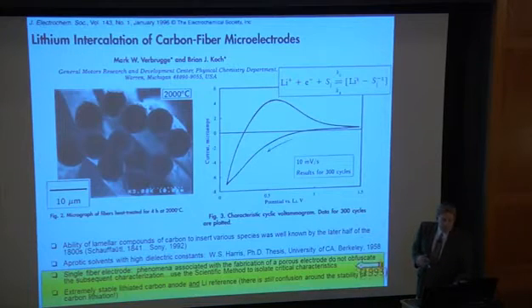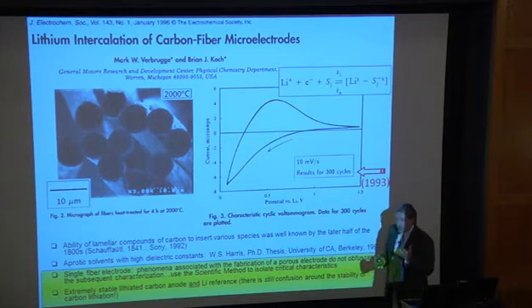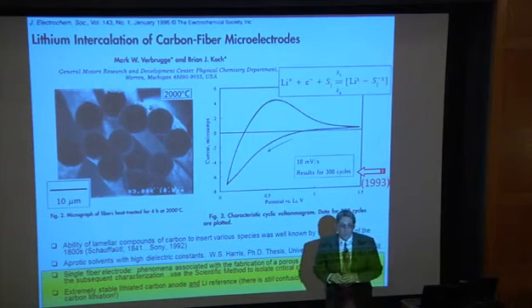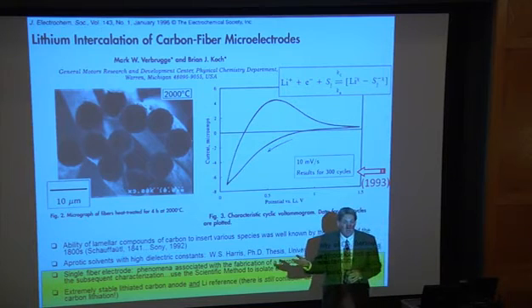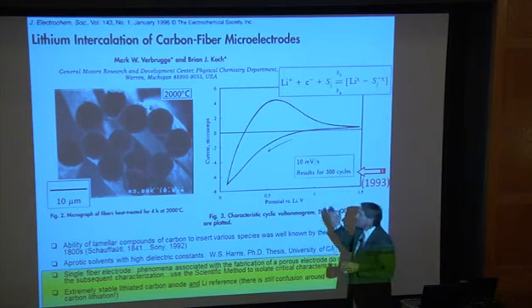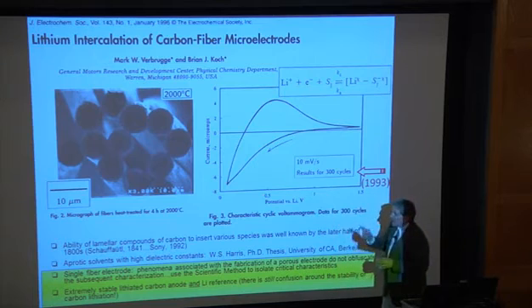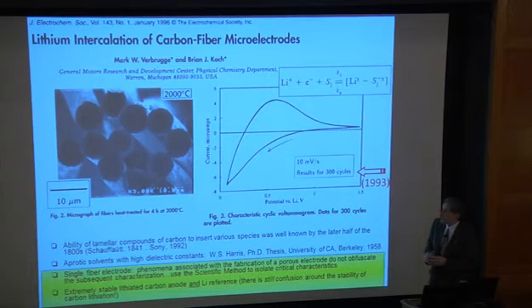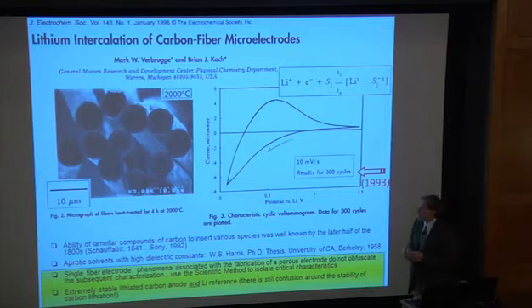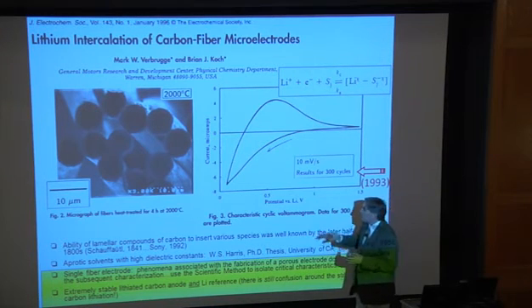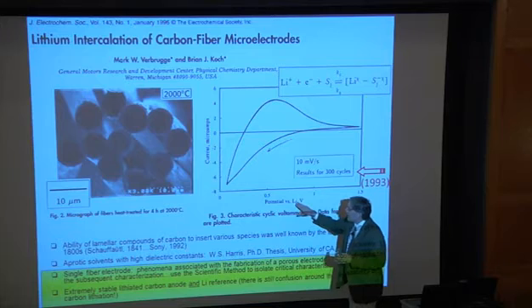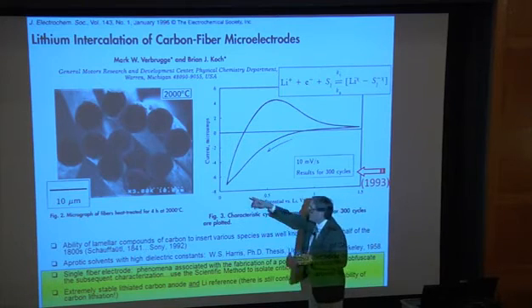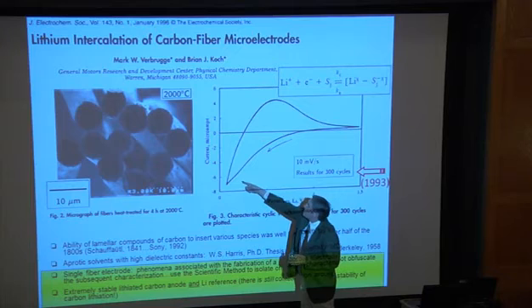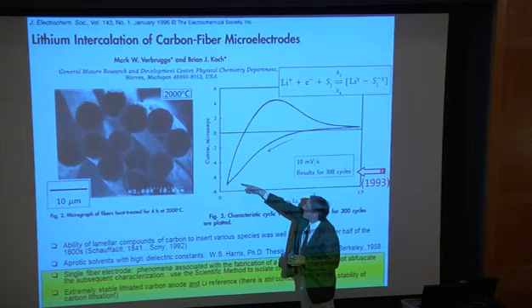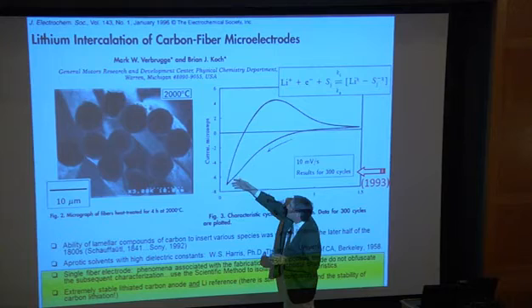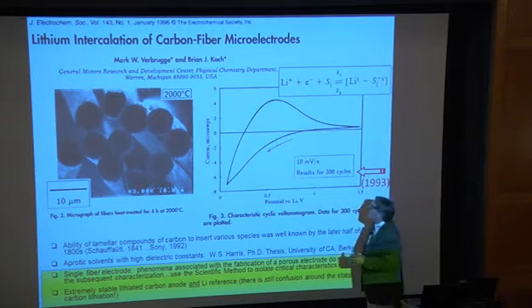So for those reasons, we did this study where we convinced our management within General Motors that we ought to switch from lithium metal to lithiated carbon. That was about 1993. This was a piece of data where it's a cyclic voltammogram, again, on the same single fiber electrodes that are used as active materials in lithium-ion batteries, one form of active materials for graphitic materials. And so we have potential being scanned in a triangular potential source here. We're measuring the current. This is lithiation, delithiation. So the lithium's coming, it's lithiation, charging the electrode, and then delithiation at the top, taking the lithium back out.